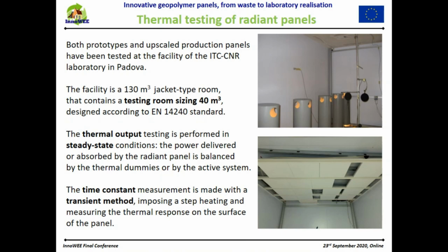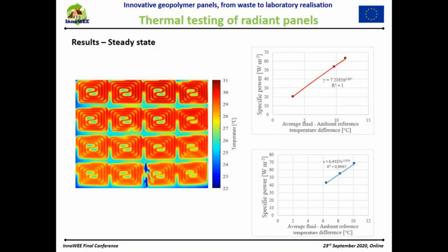The steady state thermal output, as described by the standard, is the main characteristic, but the transient measurement is also interesting, because we are able to determine the time constant to understand how fast the panels are in providing the thermal output. Here we have some results for the steady state, and the panels were tested both in heating and cooling mode. These are the red and blue curves at different temperatures of the water inlet. And the thermal image on the left shows the surface temperature of the panel during a test.